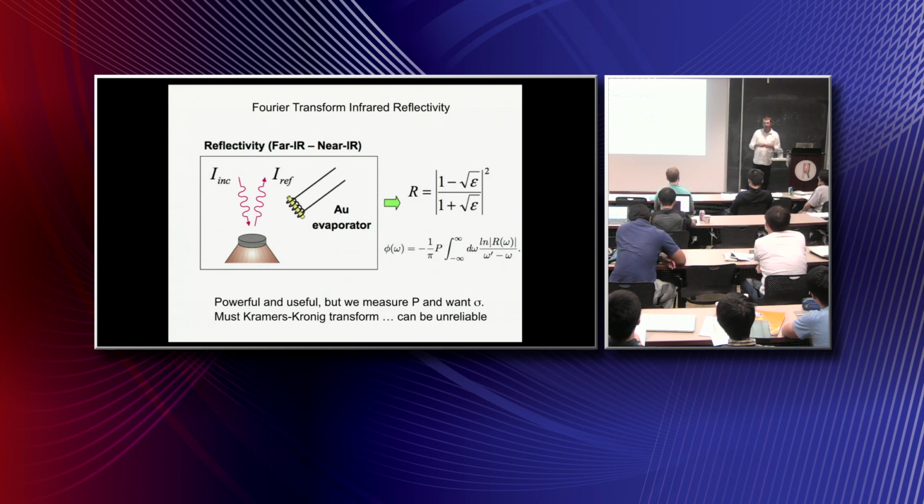What we're trying to do now with many of these time domain techniques is measure the phase directly. But in these old style experiments, we would have to do it exactly like this, where even if you cared only about milli-electron volt phenomena, in order to do this Kramers-Kronig relation the limits of the integral are infinity. You can't measure up to infinity, but you need to measure really, really high and then extrapolate like heck on the high frequency side to do this integration numerically. Then you can get the phase out. But it introduces all kinds of errors as well as being very inelegant. Why would you want to measure 10 electron volts when you're dealing with milli-electron volt phenomena? You're off by a factor of 10,000.